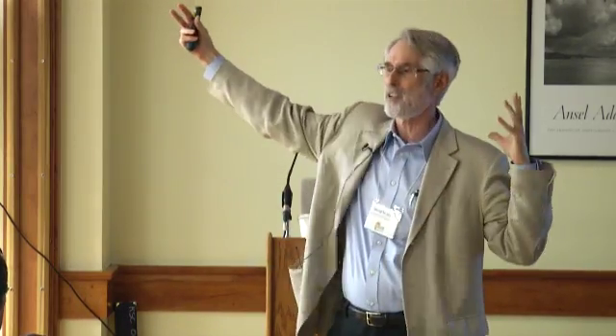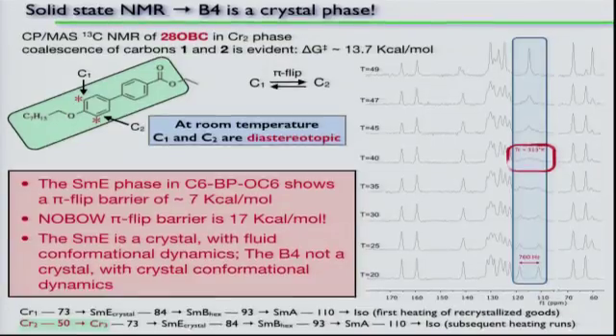And I think one of the characteristics of crystals is that they are slow to nucleate but very fast to grow. This is often true, and you often get spherulites when that happens. Not necessarily, but out of solution they come out as a kind of spherulite, I think. But really the reason you get those huge homochiral domains is, believe it or not, all the nanofilaments in one of those domains, they all came from an original single nucleus.